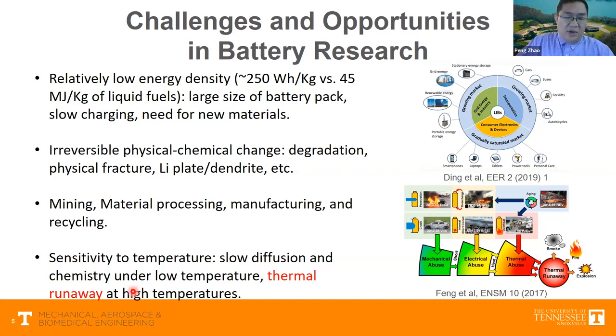The last one, which is what I'm going to focus on in today's talk, is the sensitivity to temperature. So batteries, like humans, only function well within a reasonable temperature range. Under low temperature conditions, it suffers from sluggish chemistry and manifests with very high internal resistance and very low output power. Under high temperature conditions, thermal runaway can be triggered.